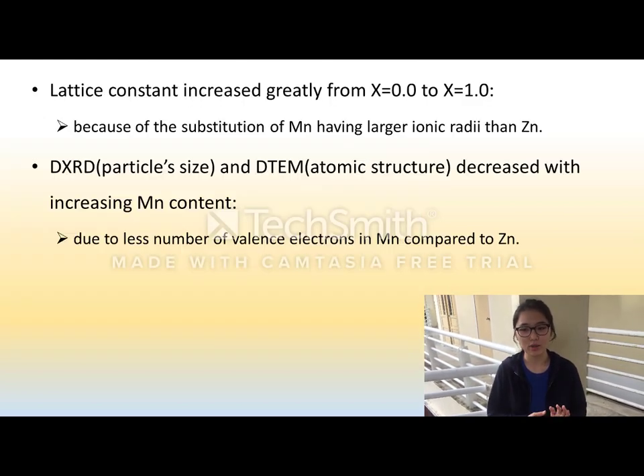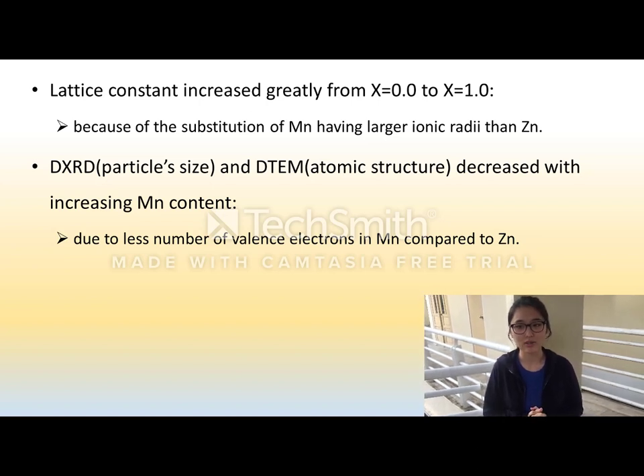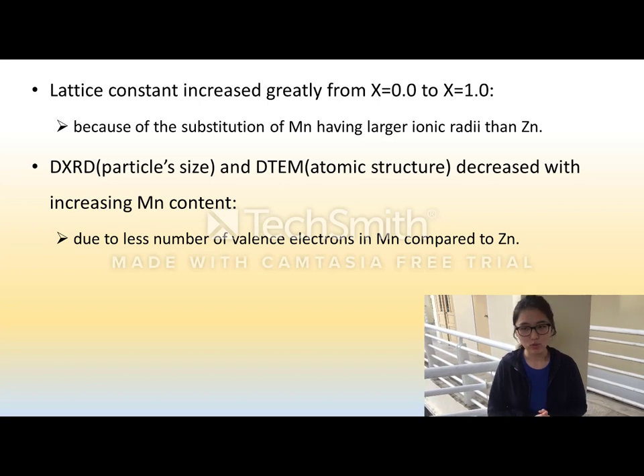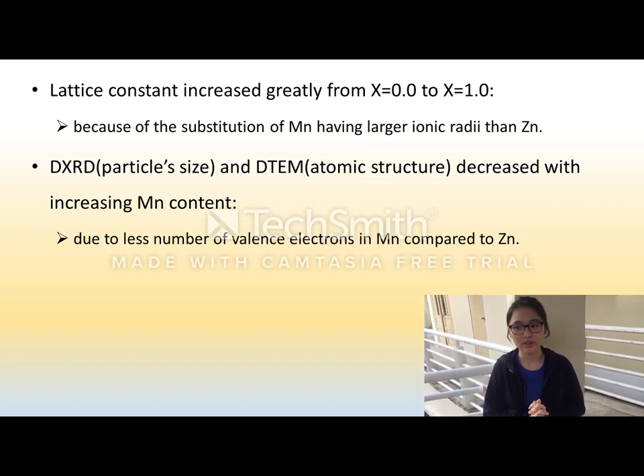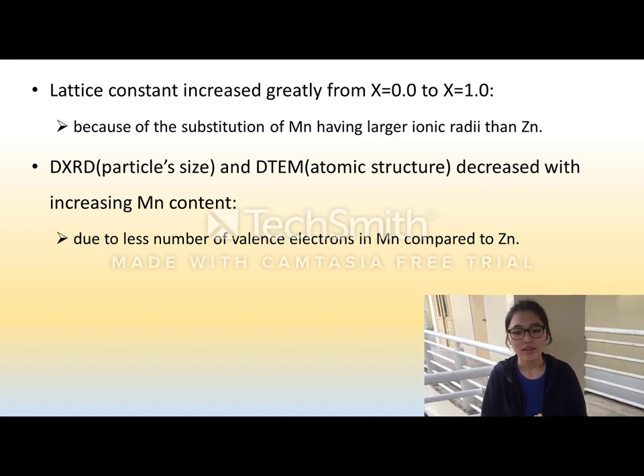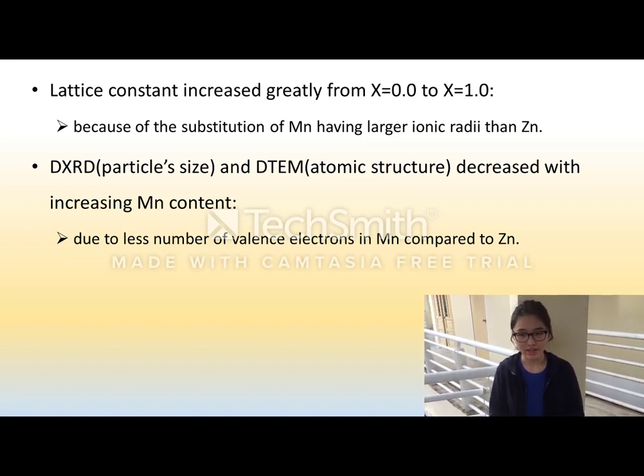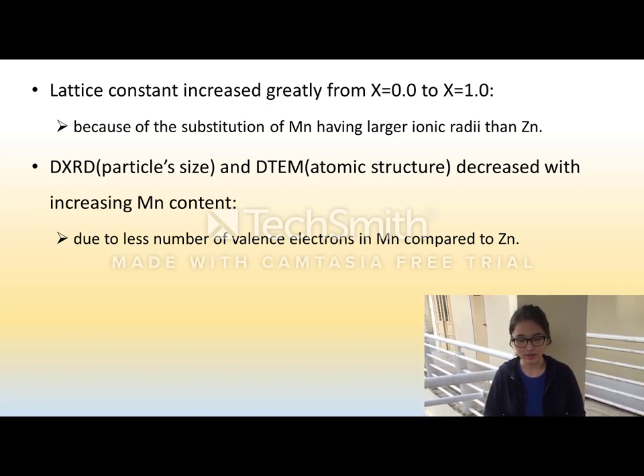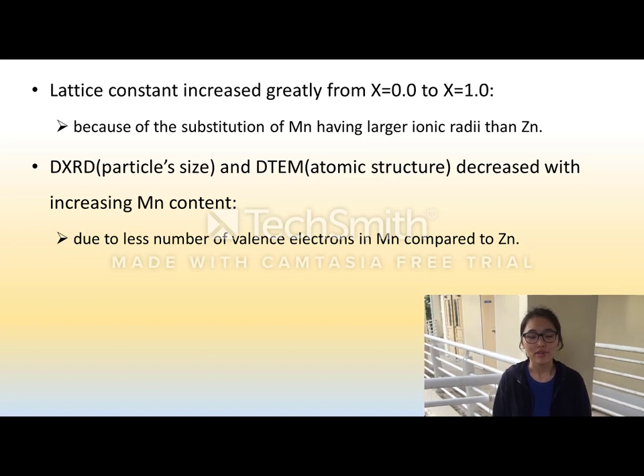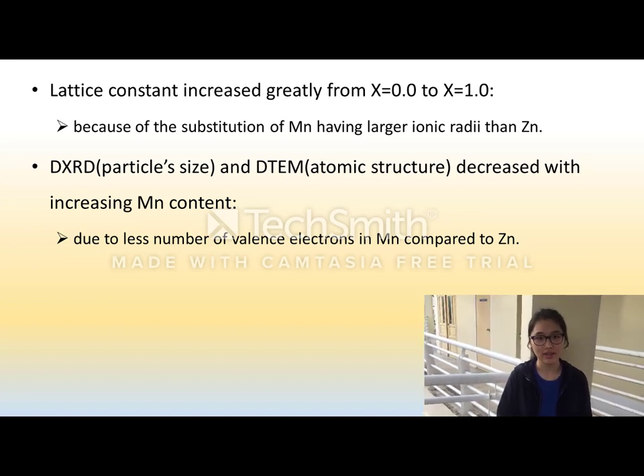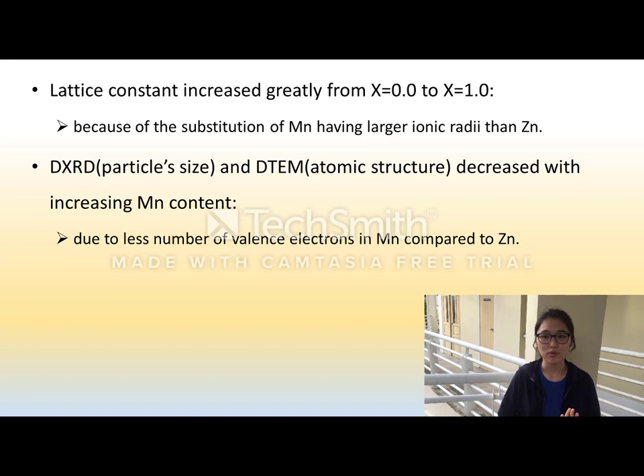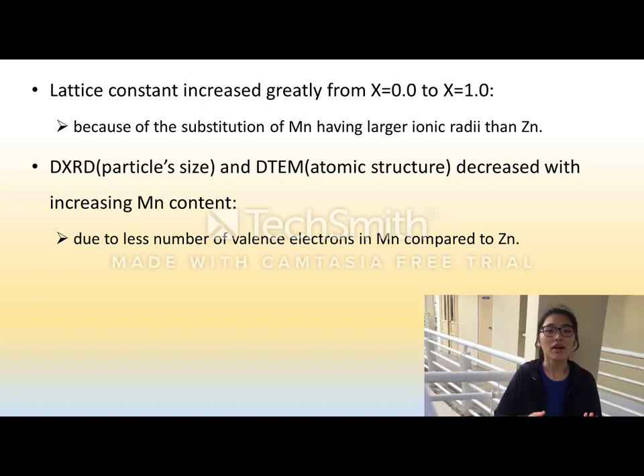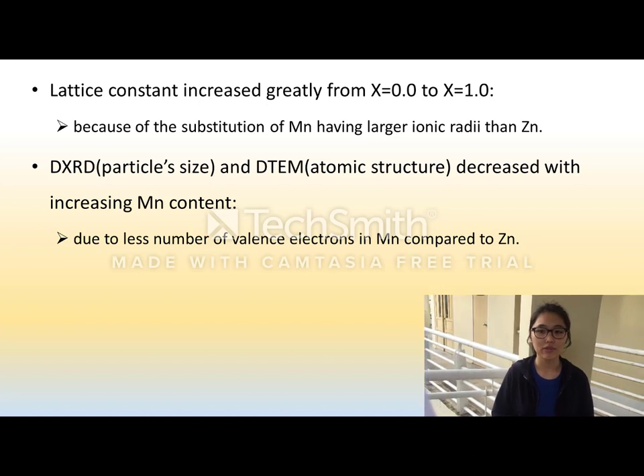We can say that the lattice parameter increase is due to the dissolution of manganese in the spinel structure. Manganese has a larger ionic radius than zinc. However, the particle size and atomic structure of the nanoparticle is getting smaller and smaller by increasing the concentration of manganese substitution. This is because the atom of manganese has fewer valence electrons. Thus, the attractive force between the nucleus and the valence electron is bigger. The interatomic distance becomes smaller, and finally the volume becomes smaller too.